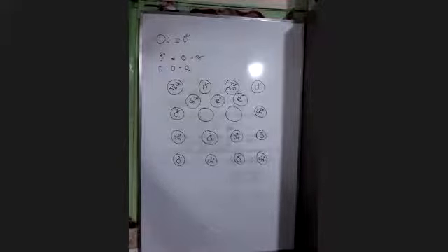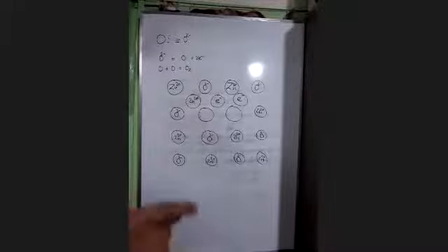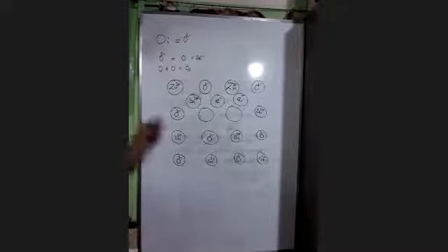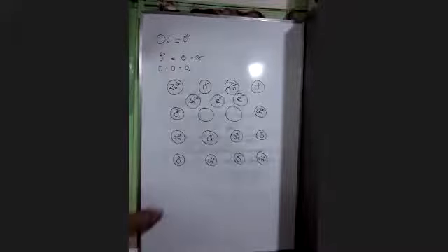But what is the difference between this and the earlier case? In the case of the F-center, we find electrons occupy the anionic vacancy, exactly the place where chloride was. But in the case of heating zinc oxide, we find that because of thermal vibrations, the electron as well as the zinc move from their own place and occupy the interstitial space. So this is another one.